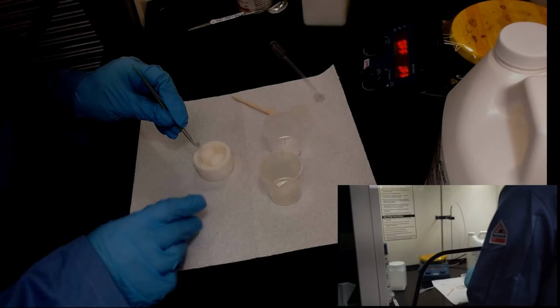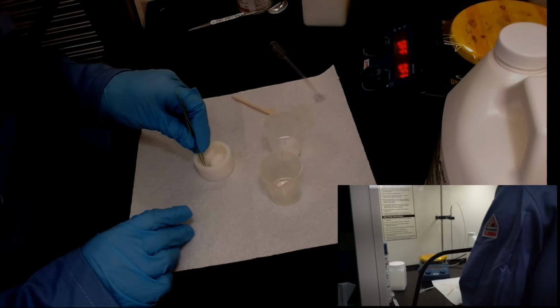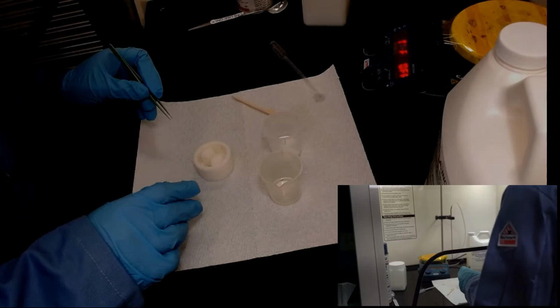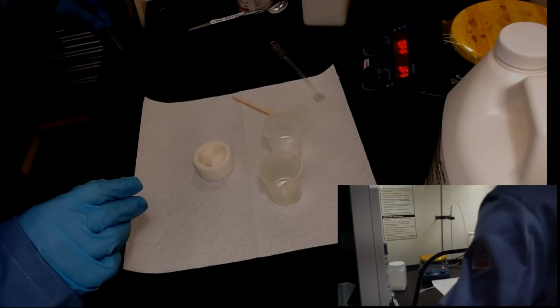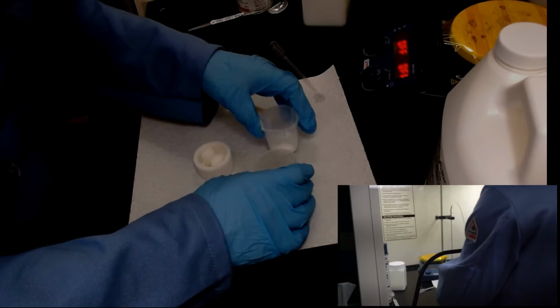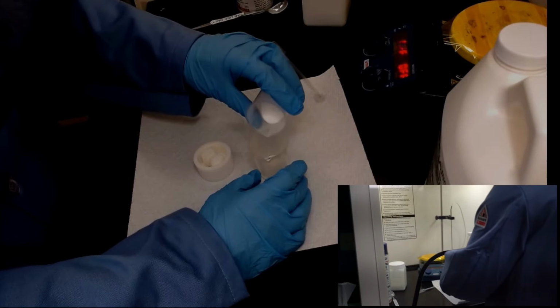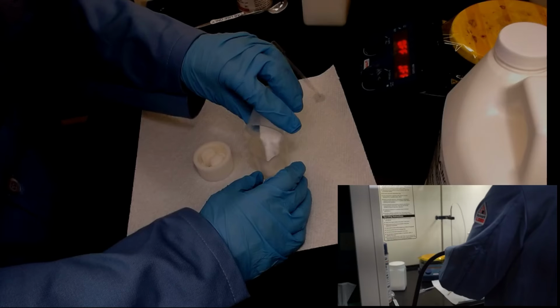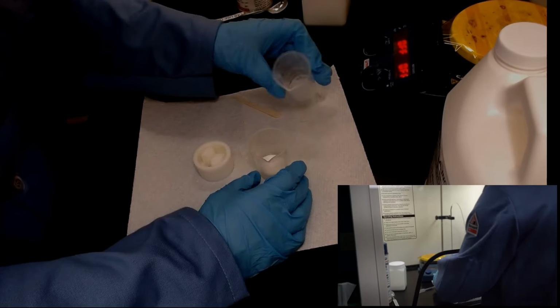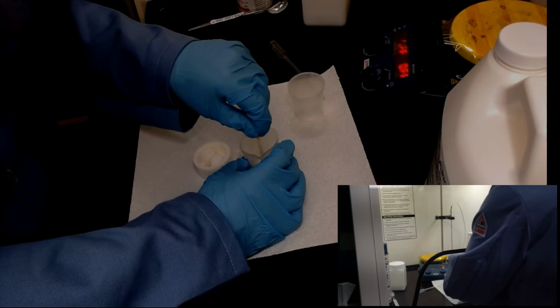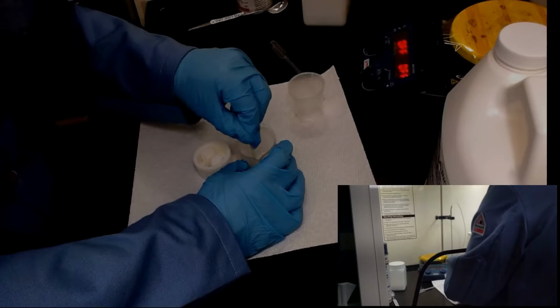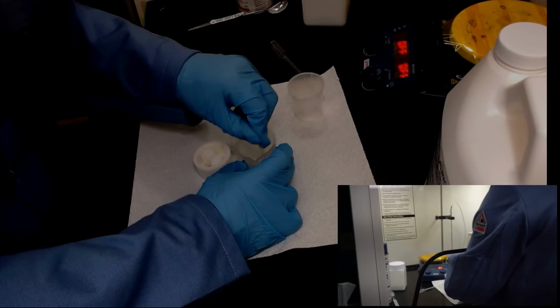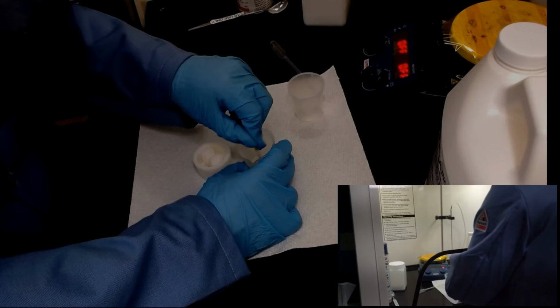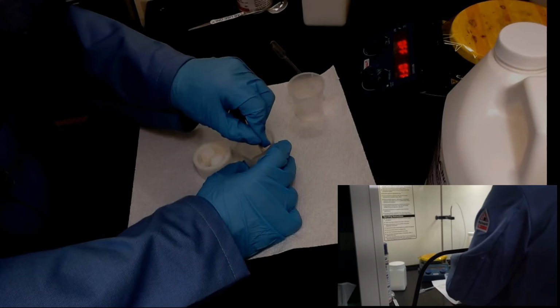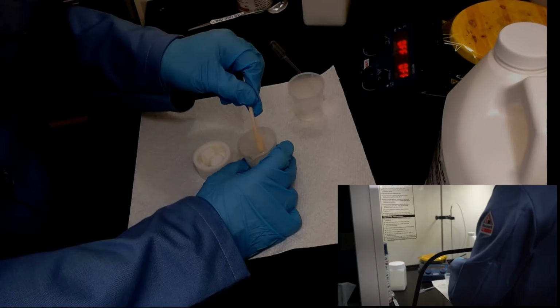And now we've got the components measured individually, so we can put the sample in the mold and then begin to actually mix the resin. You do want to be a little bit cautious mixing it and not stir too vigorously. Obviously, the components need to be thoroughly mixed, but if you stir too aggressively, it will incorporate air into the mixture, and then you get bubbles, and you can get voids in your mold.